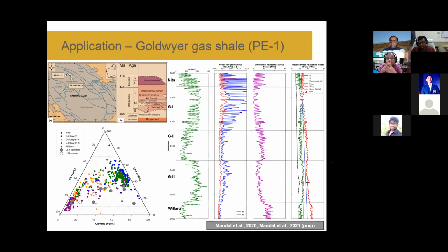And not only this study, I think all the previous studies already reported that if you do a single stage on the same sample and if you do a multi-stage on the sample, none of these properties vary beyond 2% of the original magnitude. So it is well known that if we go for a multi-stage triaxial, there is a 2% uncertainty. We already considered that fact in our conclusion and discussion section.